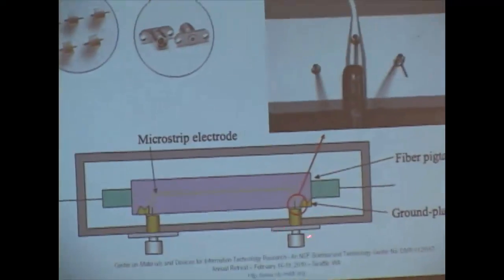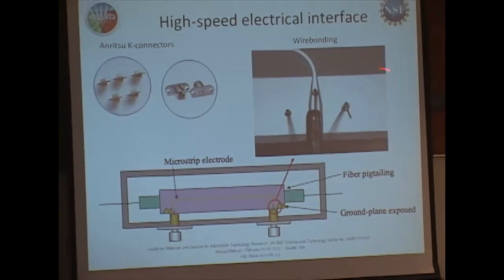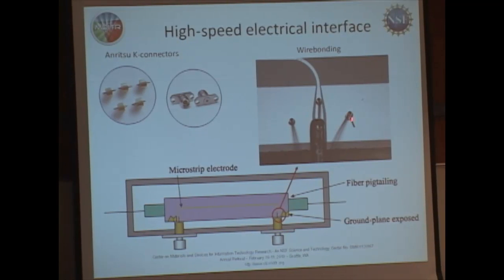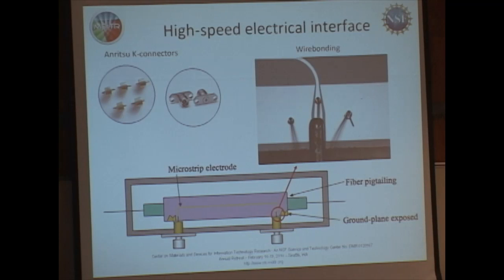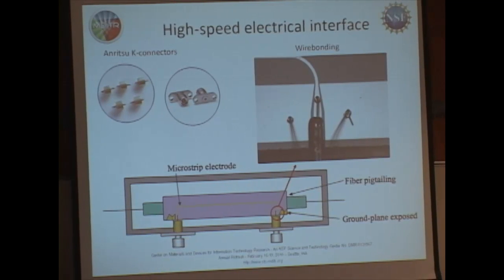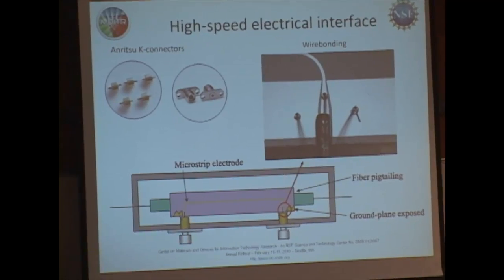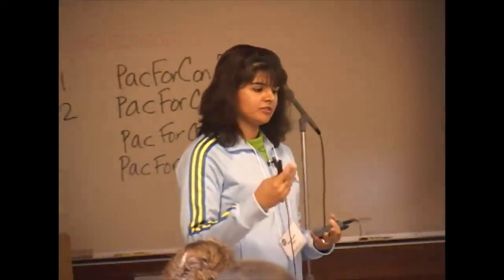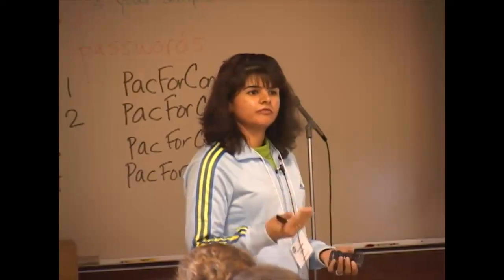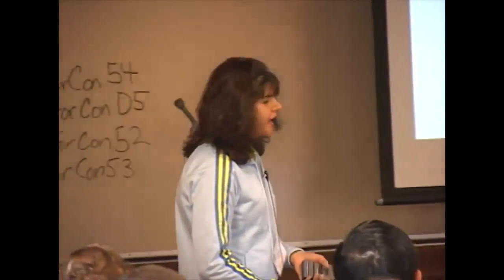And here's a little cartoon of the modulator with the fiber blocks and the K connectors. And so basically, this is a picture of this pin right here. And these 2 are the grounds, and that's the center pin. And we can wire bond to it. And if you guys are not familiar with wire bonding, basically it's just vibration on top of a heated substrate. And so we can heat up our substrate only so much, because then the chromophore would go out of its poled state. And so we work at a low temperature, and we have a new edge bonder that works really well for this. And so here's our package picture that I showed you in the beginning.